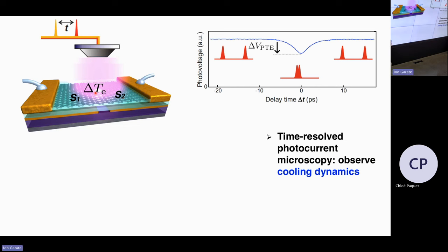Now, an interesting thing you can do for more fundamental studies is that you can, instead of shining just light on it, you can shine pulsed light. And you can come with two pulses that are both ultra short. So they have a time scale, let's say, of tens or hundreds of femtoseconds. And they come with a little bit of a delay in time. And then you can study the actual dynamics that are happening in the system. So what happens is that at delay time zero, that means that both pulses are coming at the same time, you generate a little bit less photocurrent than when these two pulses are coming very far apart. The reason for this is that it's a little bit nonlinear. So if they're coming very far apart, they're each contributing independently. So you get a little bit more photocurrent generation if they're independently contributing than when they're contributing right at the same time because of this sublinearity.